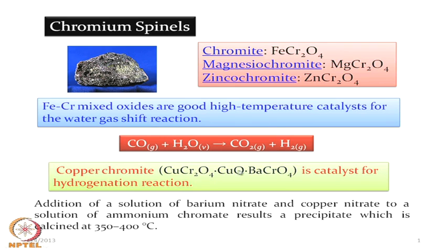So, some mixed oxides are formed, like our typical examples of different superconducting oxides, which are also different mixed oxides of, say, perovskite or any other type of solid state structure. These mixed oxides of superconducting type can be formed and can only result at a particular calcination temperature, because the dried precipitate can be heated at 350 to 400 degree centigrade for the typical calcination reaction.